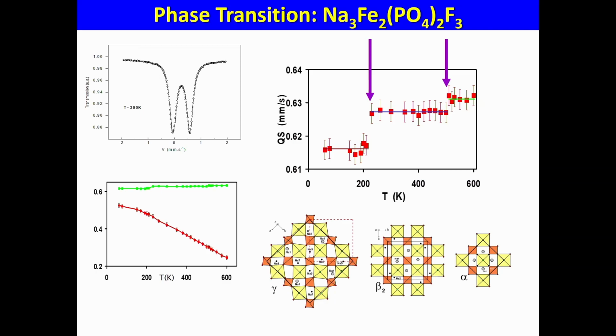And you can see now, in this case, the octahedra are dancing, samba, and now they stop. So that means very, very small changes. And after, there was a change in the position of one ion. It was possible to detect such a phase transition from Mossbauer. That means the technique is highly sensitive.